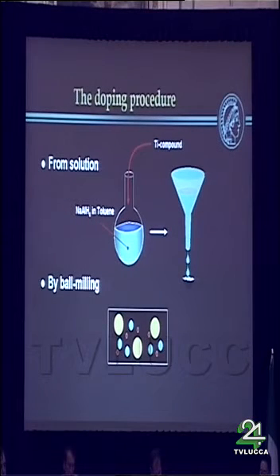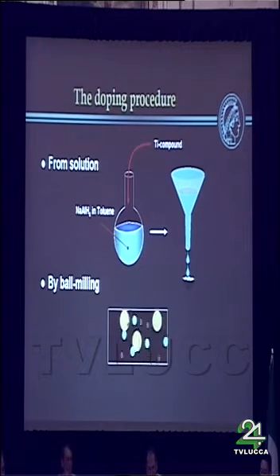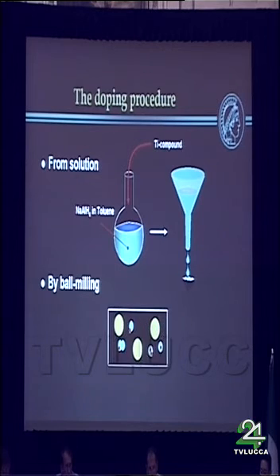How do you make the materials? The original work by Manfred Schwikardi and Boris Bogdanovich was a solution doping, but about 3 years later, Zidane and one of our chairmen, Craig Jensen, developed the ball milling procedure, which is basically the preferred method used nowadays. I think basically everybody working on sodium alanate and alanates is using ball milling to synthesize the materials.